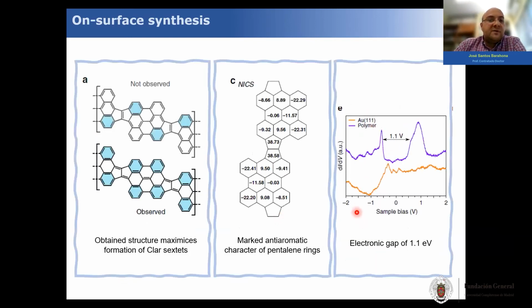Well, we confirm that the aromatic structure is the one shown here at the bottom of the slide, the one showing the maximized number of Clar sextets. For those who don't know what a Clar sextet is, a Clar sextet is this one. It's a phenyl ring with three equal resonating double bonds. We can also confirm by further calculations that the bisanthene has an aromatic structure, and also that the pentalene is very strongly non-aromatic, anti-aromatic, sorry. Also, we can calculate the band gap, which is around 1.1 volts.